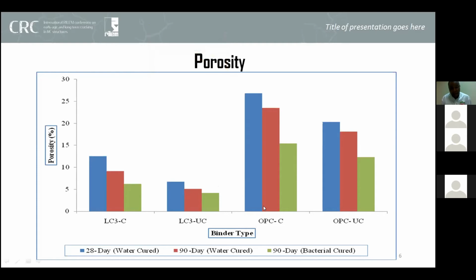However, on the other side, the materials exposed to bacterial concrete exhibited the lowest porosity, and this can be attributed to the stronger healing capacity in which calcium carbonate is precipitated by the bacteria and fills the pores in the mortar matrix. When the pores are filled, the material becomes less porous.